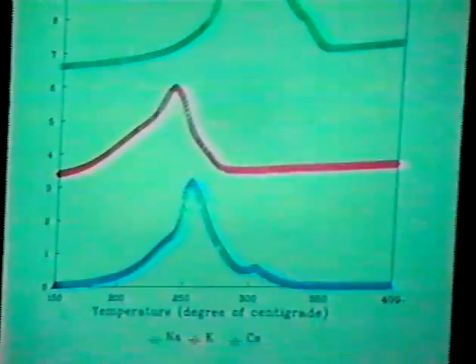So therefore we think, okay, when we did the TPR, we found something. When these three catalysts are doped with different alkaline metals, we did see different reduction temperatures. And furthermore, when we do the reduction pretreatment for the catalyst, probably some copper species still remain in a higher oxidation state. If that's true, we can probably investigate the copper species with EPR, since copper has nuclear spin quantum number 3 over 2, we probably can see something there.